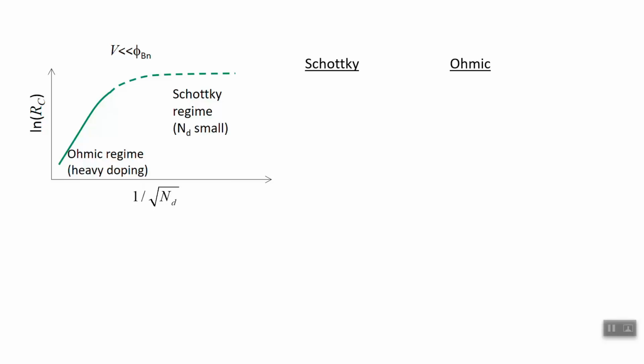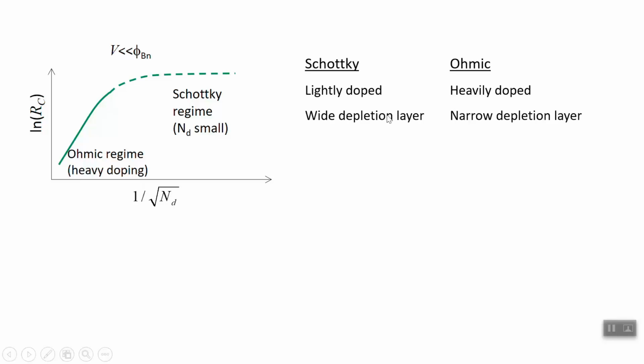Let's summarize the key differences between a Schottky barrier and an ohmic contact. First of all, the Schottky barrier is achieved with very light doping, the ohmic contact with degenerate doping or very heavy doping. The Schottky barrier has a very wide depletion layer because of the low doping, and because of the heavy doping, the ohmic contact has a very narrow depletion layer. The movement of electrons across the junction is by thermal activation in a Schottky barrier, and hence we preserve that e to the something over kT, energy over kT, in the contact resistance expression. It's by tunneling for an ohmic contact. Tunneling doesn't depend on temperature. So you didn't see temperature in the expression for contact resistance.